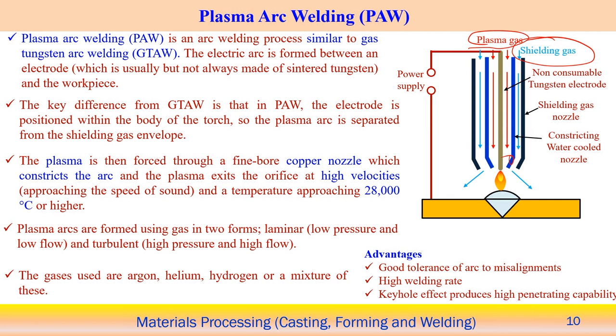The electrode is positioned within the body of the torch, so the plasma arc is separated from the shielding gas envelope. Here we can see that the plasma arc is basically separated from the shielding gas envelope, and the plasma is forced through the copper nozzle which constricts the arc, as already discussed, and the plasma exits at very high velocity approaching the speed of sound. The plasma temperature can go up to 28,000 degrees centigrade or higher, but when it interacts with the workpiece there might be loss of heat from the arc, such that the maximum temperature of the workpiece can go up to approximately 2300 or 2500 degrees centigrade in the case of steel.